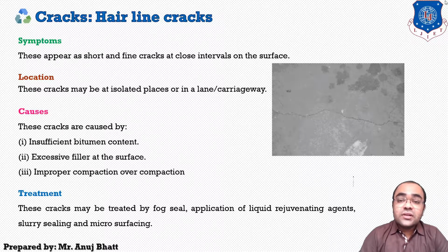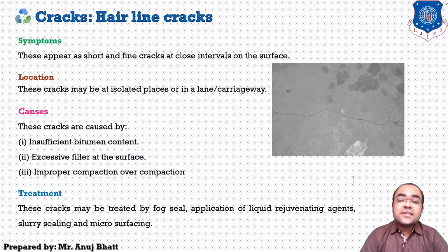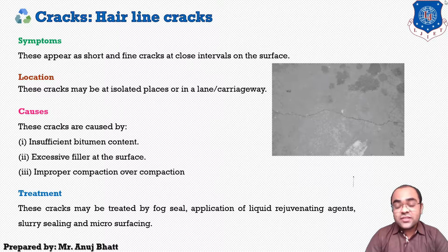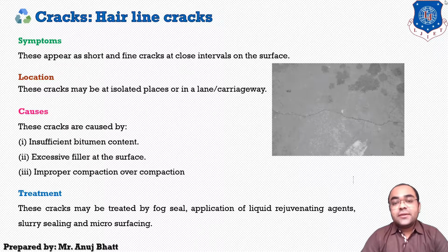If we talk about how to treat such hairline cracks, these cracks may be treated by fog seal or by application of liquid rejuvenating agents, slurry sealing, and microsurfacing. You can also provide microsurfacing so that such cracks can be eliminated.